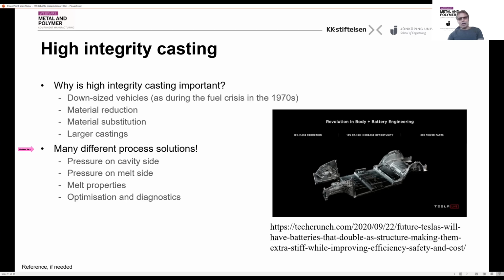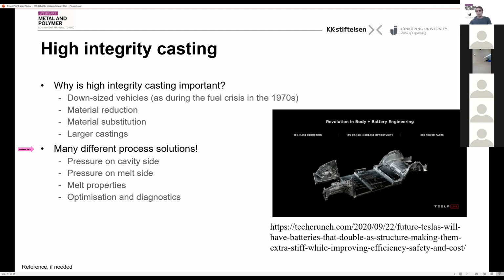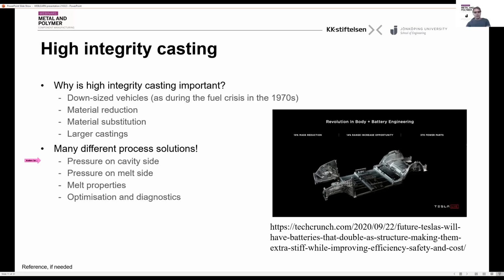So there are many different ways of achieving high integrity castings. If we look at it from a productivity standpoint, most of the casting processes are capable of sufficient volumes, as for instance for the automotive industry and for the electronics industry. These are pressure-driven casting processes. When you look at the ability to create a high integrity casting, we have the pressure in the die cavity as one of the parameters, because we can suck in the melt, or we can empty the cavity, because the atmosphere in the cavity is one of the problems. We can work with the pressure on the metal side, that means increasing the pressure. And the difference between the cavity and the metal side is also very important, because that drives the filling process. We can also work with the melt properties in order to change the behavior of the melt.